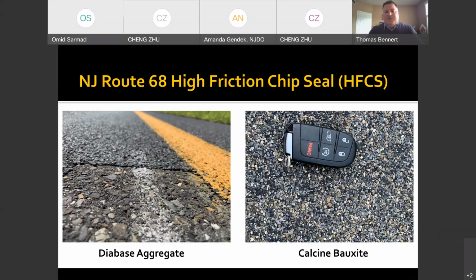You can see some pictures we took of the surface. On the left there is the diabase material. You can see how thin of an application it is. That is, again, the diabase material. And the photo on the right is the calcined bauxite. So again, it's a very fine aggregate. It's essentially a one aggregate size, approximately 100% passing the quarter-inch sieve, and provides a very durable and hard pavement surface for safety reasons.